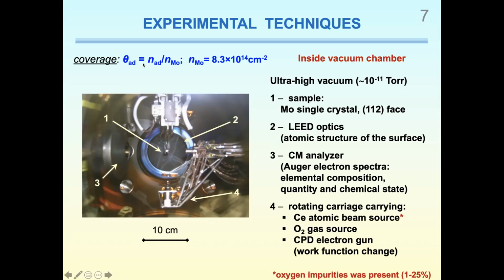The cerium coverage was defined as a ratio between surface concentration of cerium atoms and surface atoms of molybdenum (112) face. The coverage value was considered to be proportional to the cerium deposition time. This rate was calibrated based on the analysis of some simple LEED patterns as well as work function values.